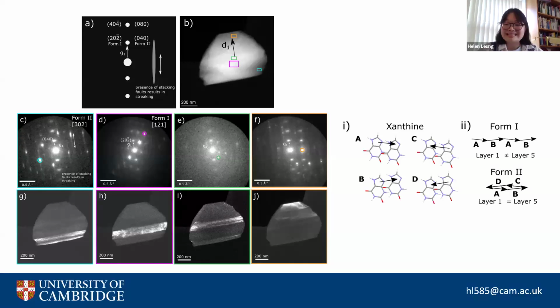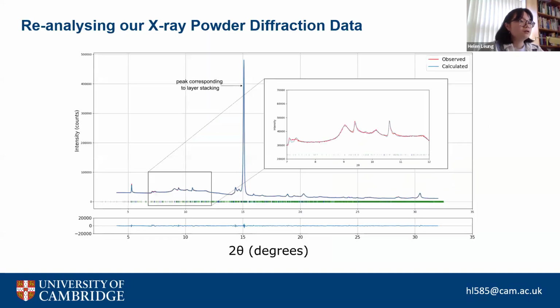So the last thing that we did is we started to look at how we might want to model that back onto our X-ray powder diffraction data that I showed you earlier, and thinking about how our knowledge of these stacking vectors can be helpful to that model. So what we did is we created a supercell of 20 layers. We just chose form 2. So those layers had a stacking pattern of ABCD, ABCD, ABCD, ABCD until we had 20 layers.